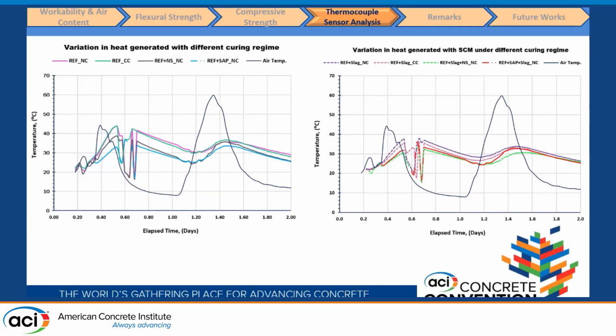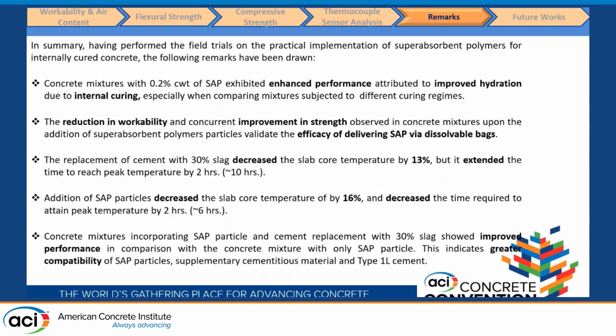We tried to evaluate the variation of the heat generated under different curing regimes. We found that the application of curing compound on the slabs had no significant impact on the core temperature of the slabs, but the addition of superabsorbent polymers reduced the core temperature of the slabs.